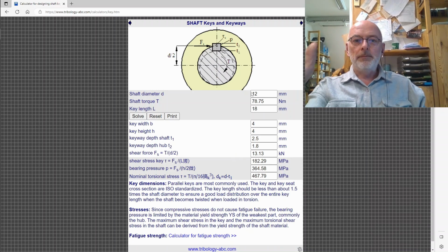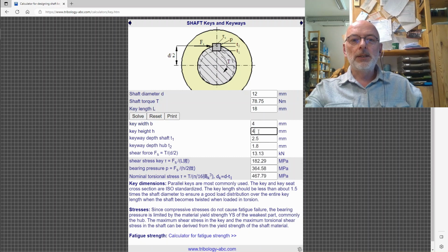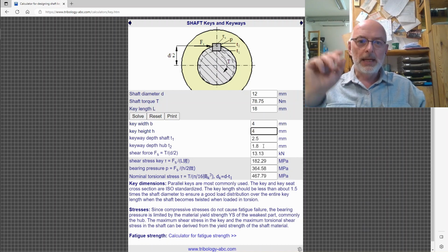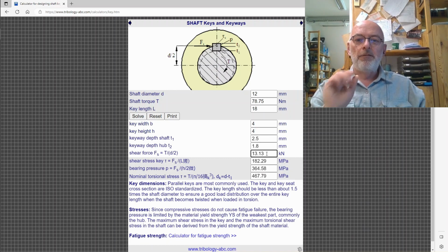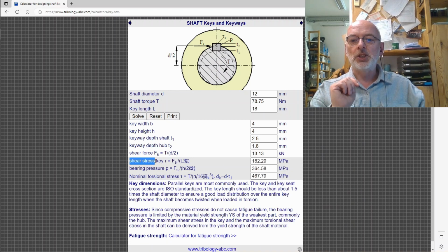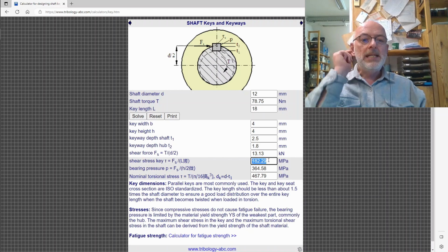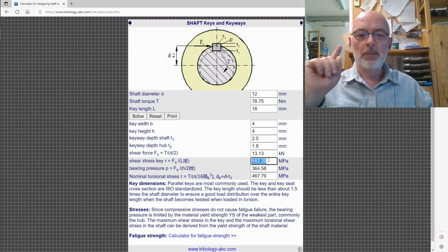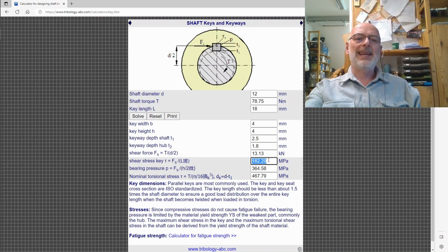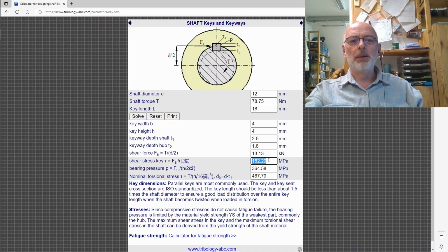So ISO with that parameter gives us a key width and a key height of 4 millimeters. Then we have, of course, to make the key ways at a certain depth. And we have a shear force of 13.13 kilonewtons, and that gives us a shear stress on the key of over 180 megapascals. Remember, 6060 can only take 105 megapascals. We have a problem here.